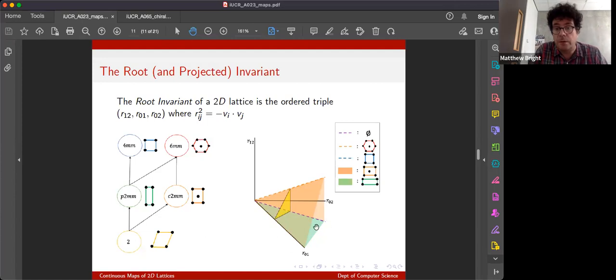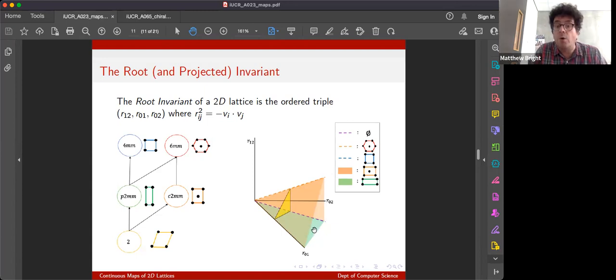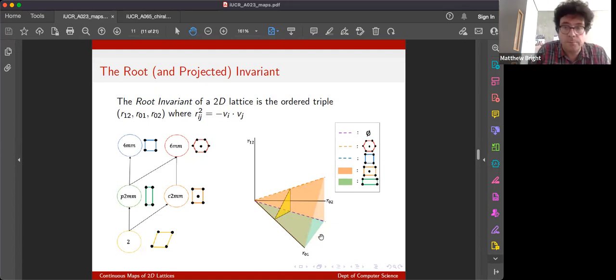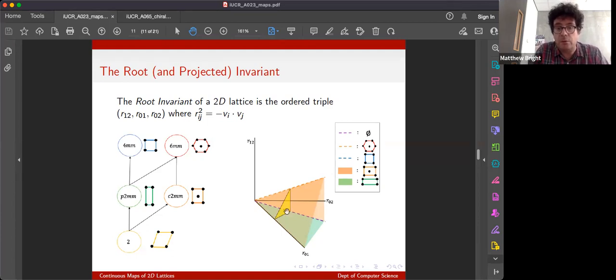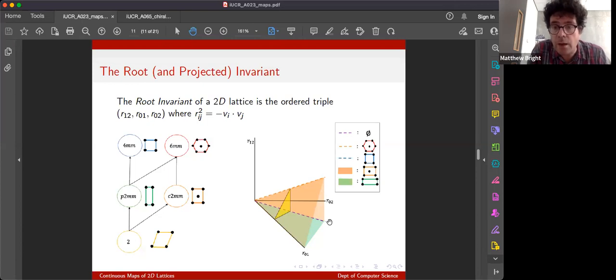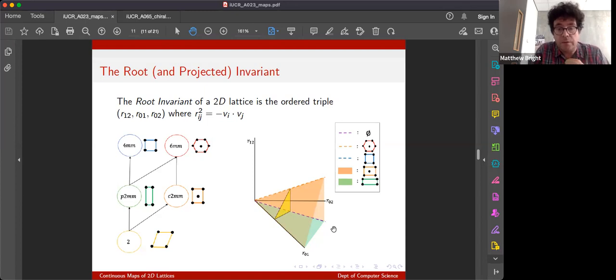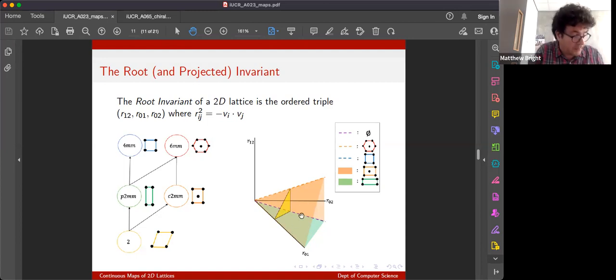So for example, if you have a primitive rectangular lattice, then one of your angles is going to be 90 degrees. So your smallest root product, your smallest R12, is going to be zero, and that's going to live on this plane here. Or in some senses, there is an empty set here, where, strictly speaking, all three, this strictly speaking means where everything is zero. But we want to, that would be an empty set, no lattices mapped there. But all lattices mapped to somewhere else in this space.